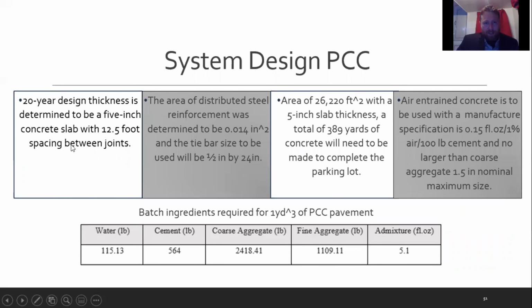The summed up design of the PCC concrete design is that it will be a 20-year thickness with 12.5-foot spacing between joints. The area of distributed steel will be 0.014 square inches with a tie bar size of 1/2 inch by 24 inch. The total area is just a little over 26,000 square feet with a 5-inch slab, needing 389 yards of concrete to finish. We'll be using a manufacturer specification of 0.15 fluid ounces per 1% air per 100 pounds of cement and no larger than coarse aggregate of 1.5-inch nominal size.